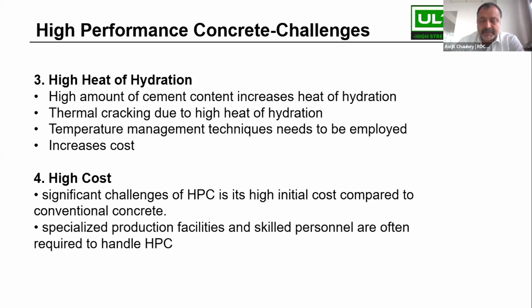So for the bullet train, we were involved in certain sections, and we came across many challenges that they were facing. One was that, despite the designers' efforts, certain portions of the girders qualified as mass concrete, where the heat of hydration is very high and was leading to cracks. This was happening because of very high cement content, leading to very high heat of hydration and then cracking or other problems. So this is also one of the challenges being faced in high performance concrete.